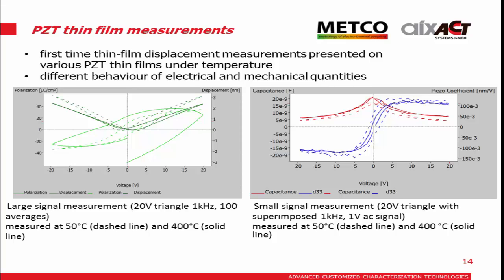This is the small signal, where we apply an AC signal and change the DC bias, so you can see what the D33 versus the applied bias does. At 0 volts there's almost no D33, but if you increase the voltage, then you still have a rather high value here.